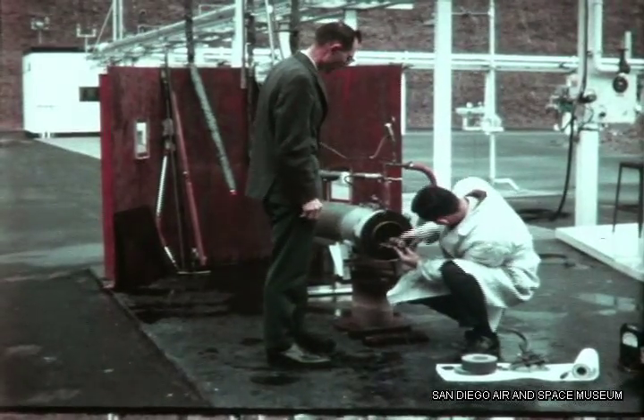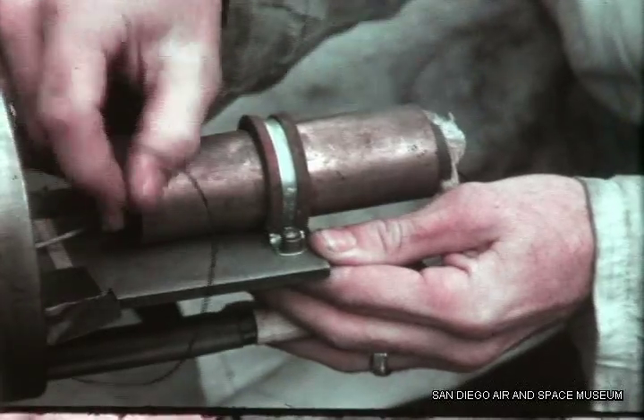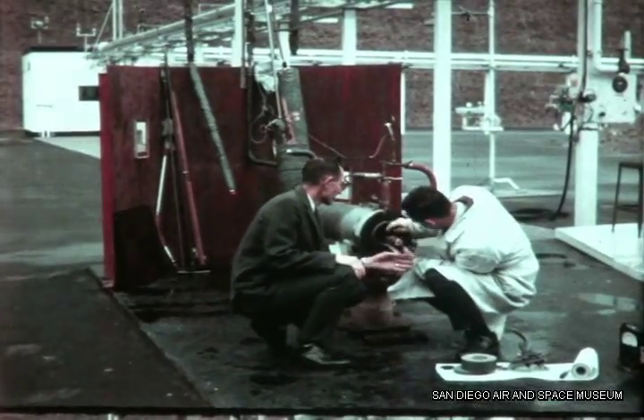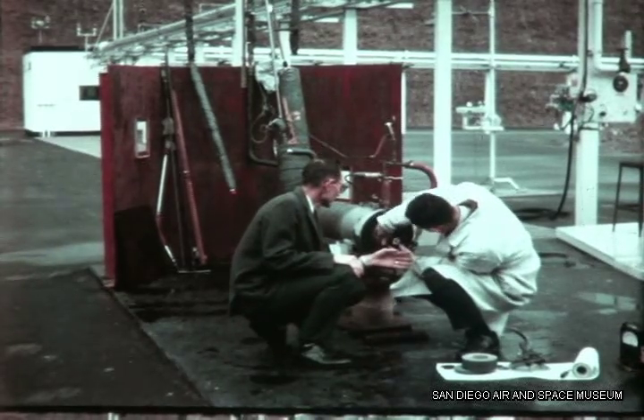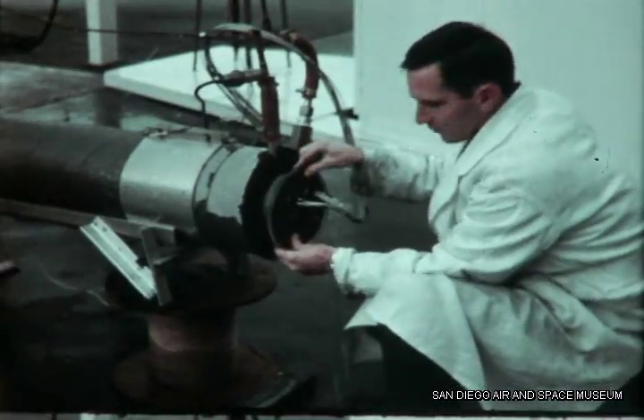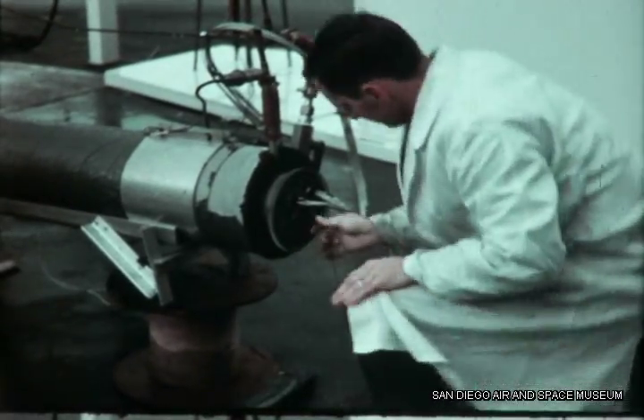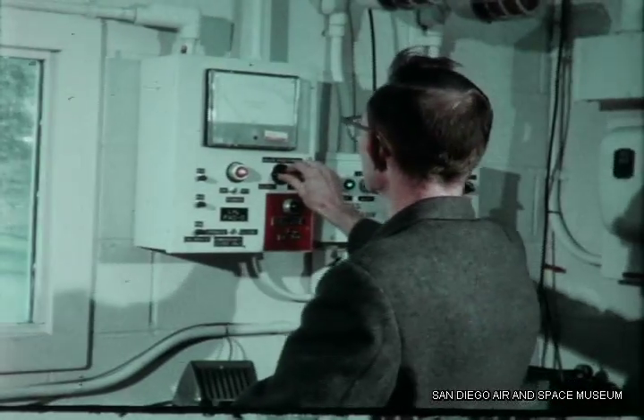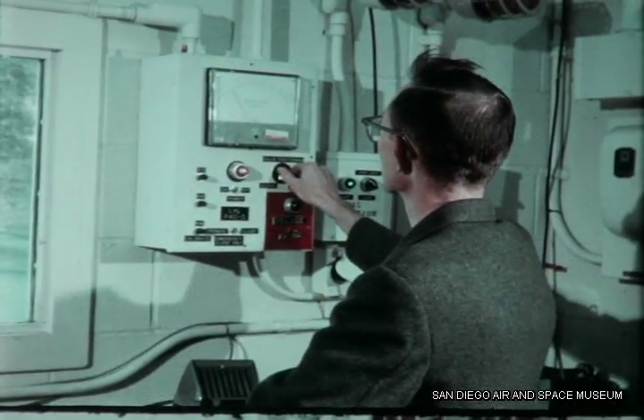For cryogenic tests, plate and charge are installed into a double-jacketed cylindrical container. Liquid nitrogen flows through the outer jacket. Liquid hydrogen, at -423 degrees, flows through a cooling tube, which is in contact with the plate of the specimen, cooling it to about -400 degrees.